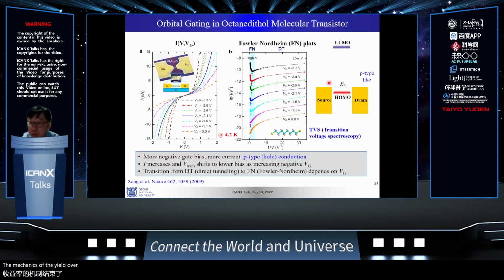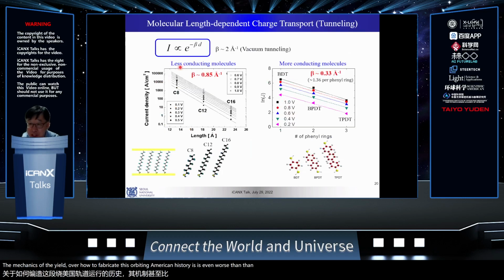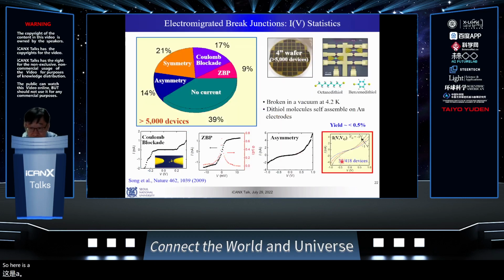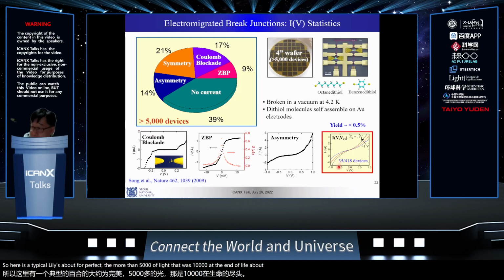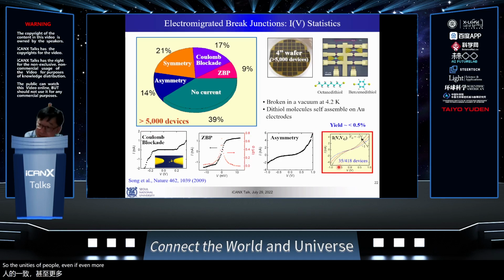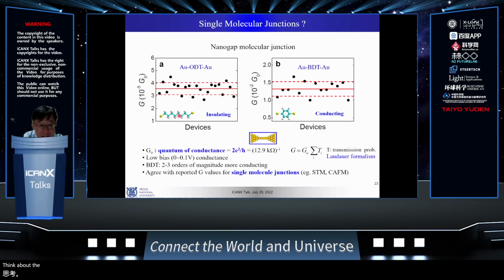The yield of how to fabricate this single molecule transistor is even worse than this structure. So here a typical yield is: you fabricate more than 5,000 up to like 10,000, and it ends up with about 30 devices working. So the yield is even more difficult for a single molecule junction. And this is all the working devices. So you can count about 35 junctions. And there is an insulating molecule single molecule transistor, and this conducting molecule single molecule transistor.